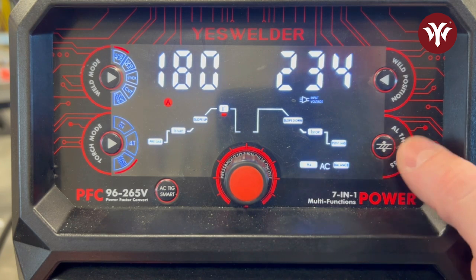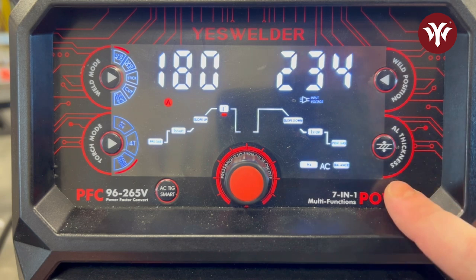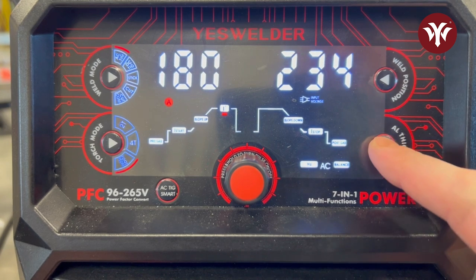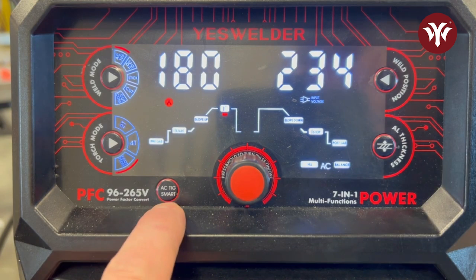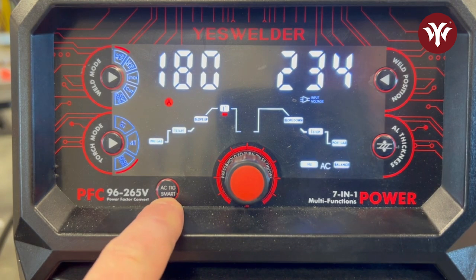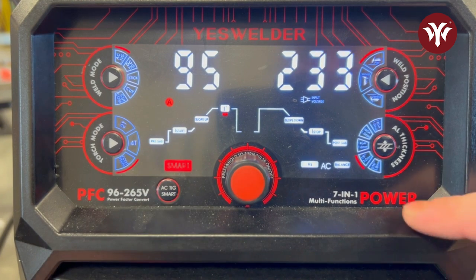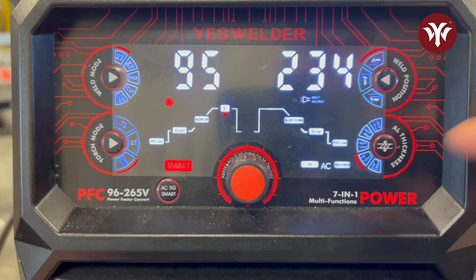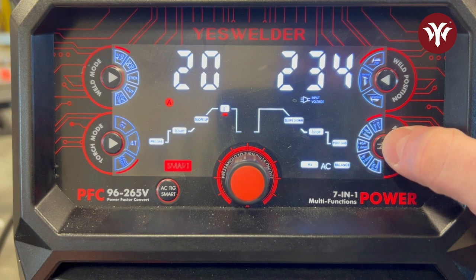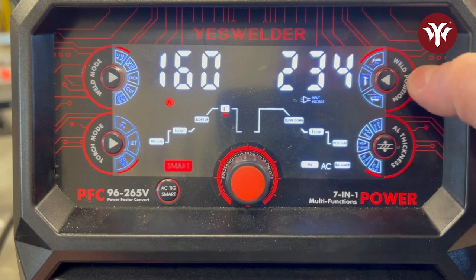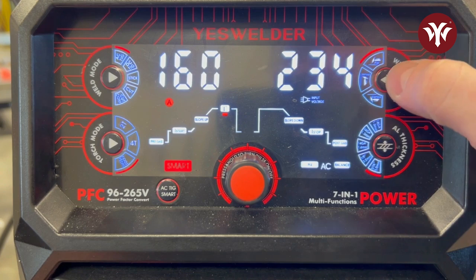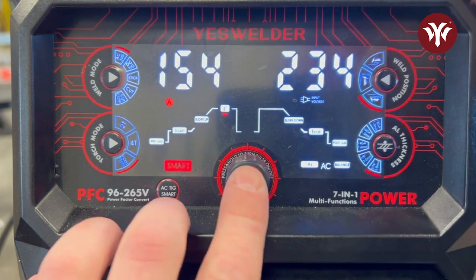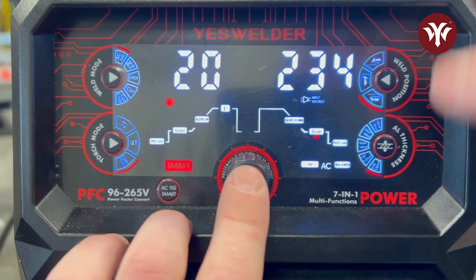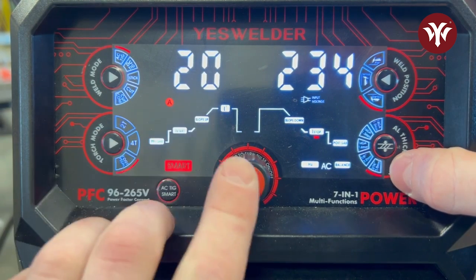So the other thing we can do is let's go check out this smart feature on the 2050. Okay, so to get the smart feature enabled, let's hit AC TIG Smart. That lights up all of our other side of the menu here. So we have everything from 18 gauge, 16 gauge, 14, 1/8, 3/16. And the weld position. If you're welding flat, vertical, or overhead, it's going to adjust the currents. And see, there you go. We're at 3/16 and it picked up the stop current.